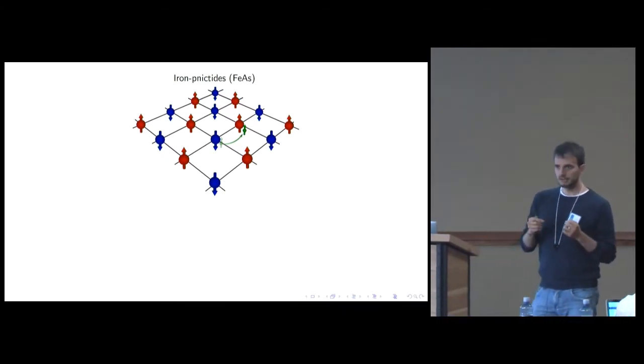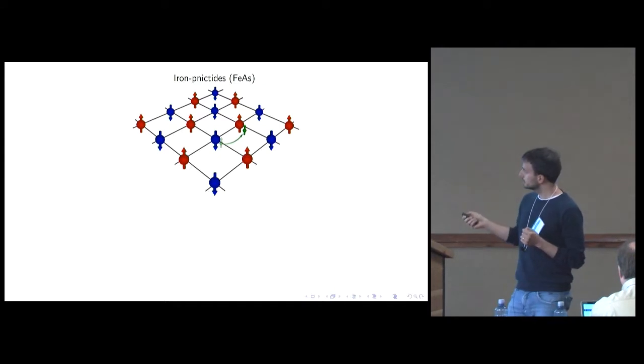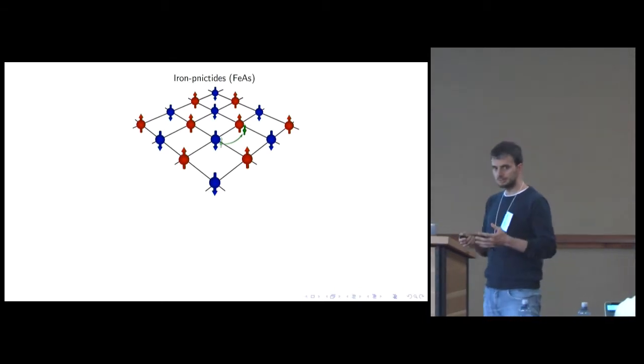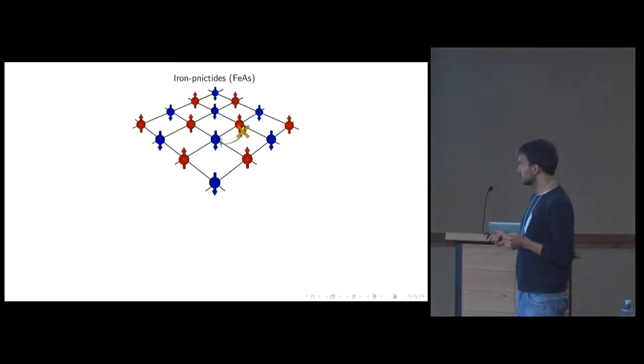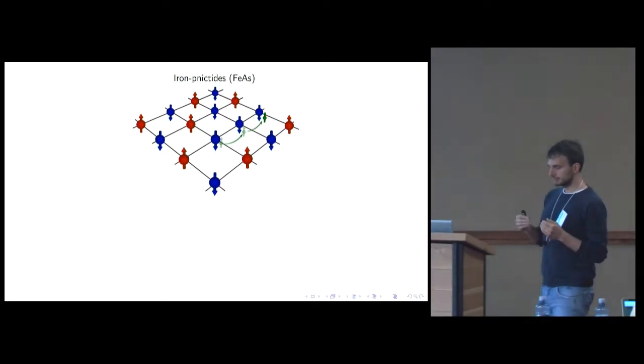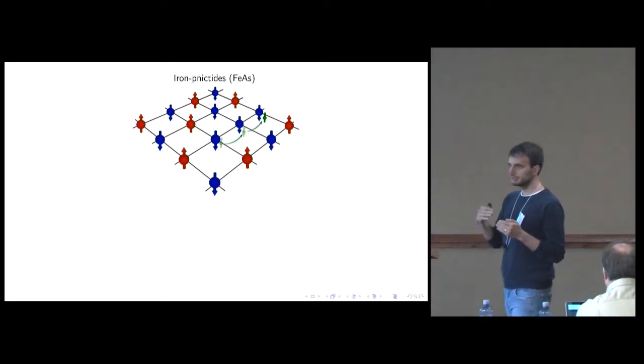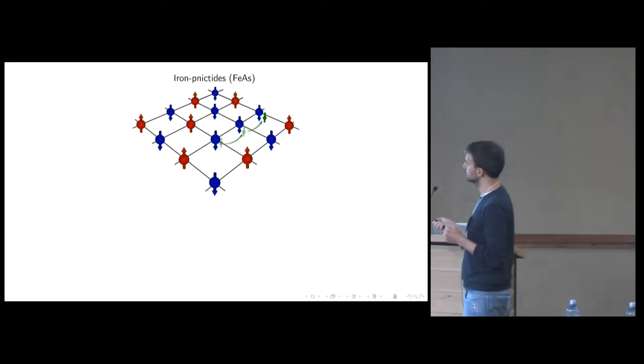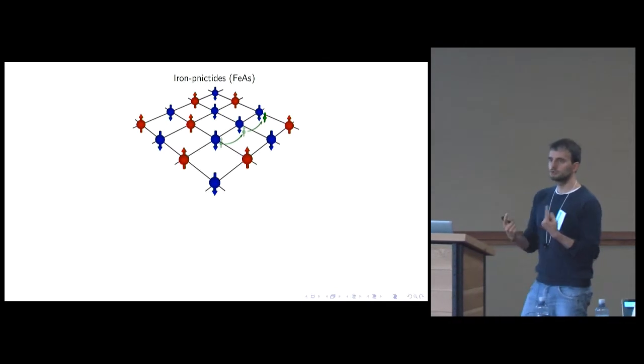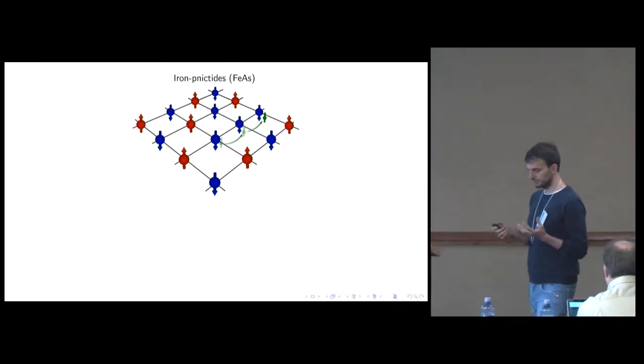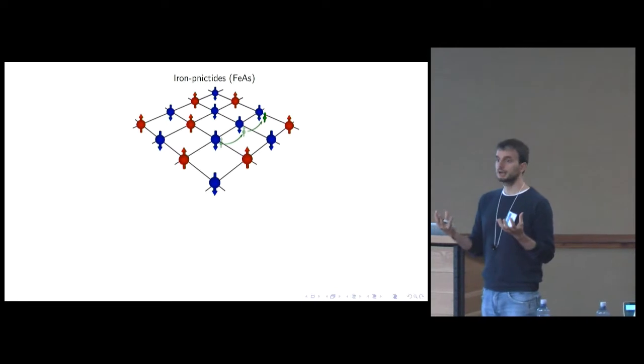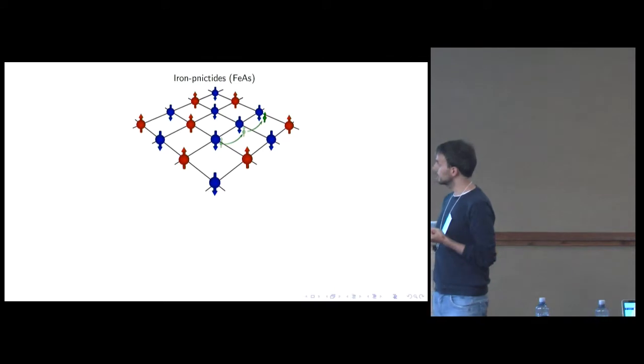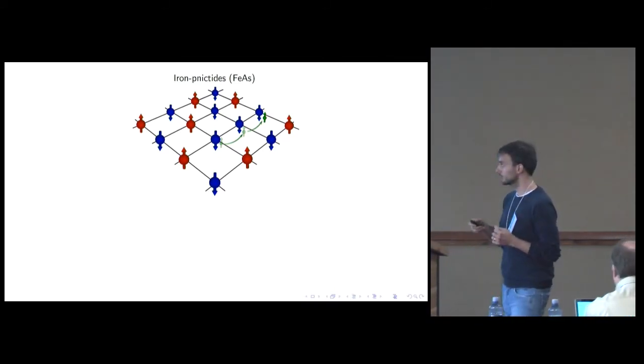And these electrons don't like to hop to atoms that have opposite alignment to the atom they are coming from, because that's energetically unfavorable. So in the end, they act as effectively transmitting or mediating an interaction between neighbors that makes them want to align with each other. So we have two kinds of interactions in this kind of system: one that favors anti-alignment between neighbors, and another one that favors alignment.